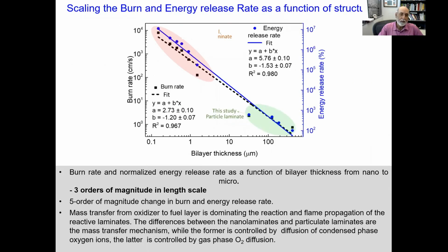So we took all the data, which is to say the laminates that are sputtered. So these are very, very small bilayer thicknesses. So those are the data up here. And then the particle layers are the ones down here. So they have much larger length separations. And you can see that you can put the burn rate versus bilayer thickness all on one curve. And the energy release rate also on one curve. So what we're doing here is we have 3 orders of magnitude in length scale, leading to 5 orders of magnitude change in burn and energy release rate.